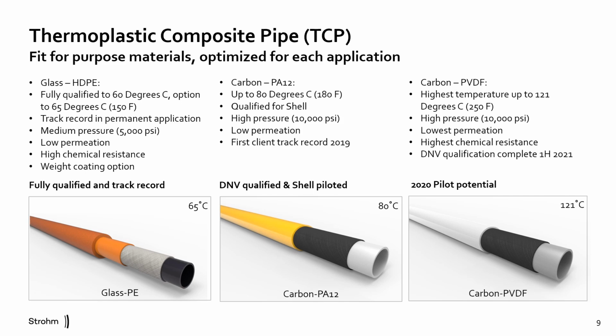While the carbon fiber provides exceptional structural properties, these materials have been specifically developed to cope with extreme conditions such as high CO2 content and sour service. All of our TCP products boast an extremely low gas permeability due to the bonded cross-section and the additional shielding provided by the inclusion of fibers, which take up approximately 50% of the volume in the composite section.